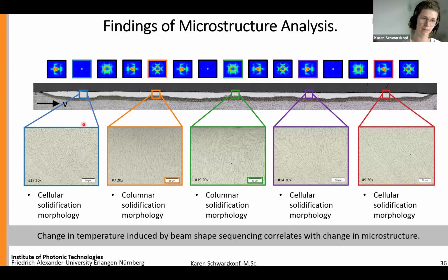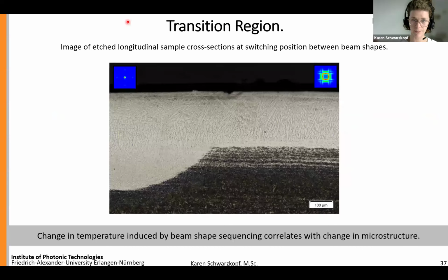Now, since we do see differences in our first glance of microstructure analysis, we also expect to see differences in our mechanical properties. And as mechanical property, we were investigating the hardness level. And we basically were measuring the hardness along the center line here. So basically here. And the result is shown on the next slide.